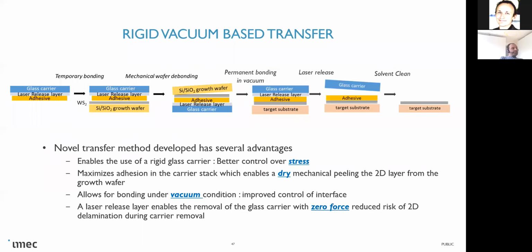The next step that we need to understand to upscale is, assuming that we grow on an epitaxial flat surface and that we have a very high quality, close to single crystalline material, how will we transfer that layer without building in plenty of strain and all kinds of uncontrolled interface defects? Therefore, at Imec, we developed what we call a rigid-based vacuum transfer. Rigid, why rigid? Because we think that this is a way to control at least the strain during the transfer.